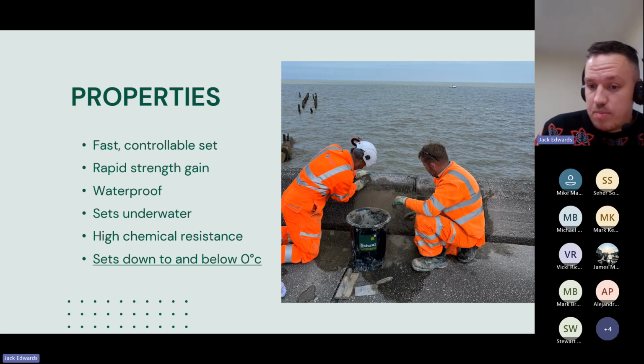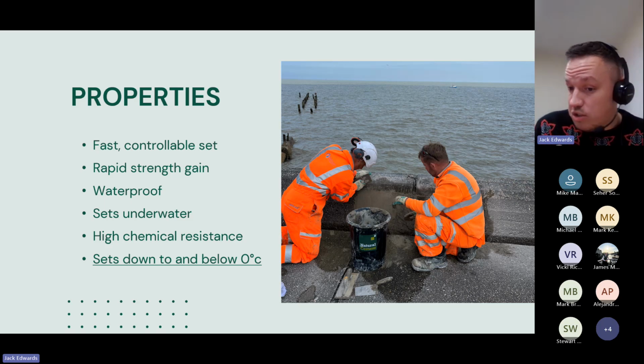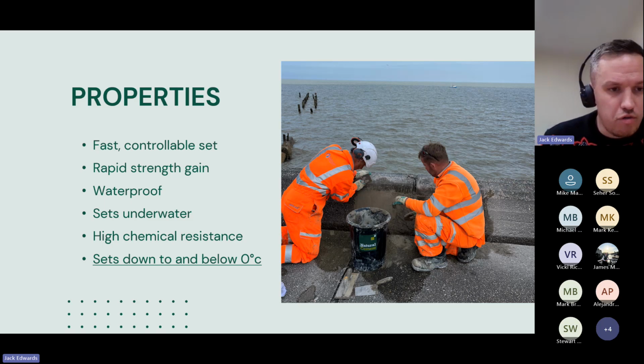Beyond that, when the material is set in 2 minutes, obviously you can't do much else with it. So one thing we do add is a retarder to delay that setting time and achieve a more workable mix, and then make that into the other products that we supply. The retarder that we use in the natural products is citric acid, which I'll run through shortly.